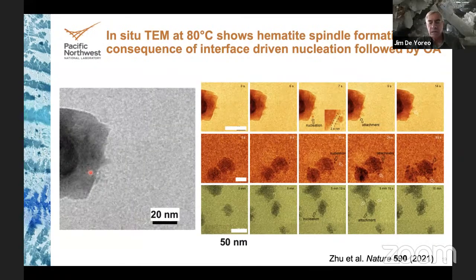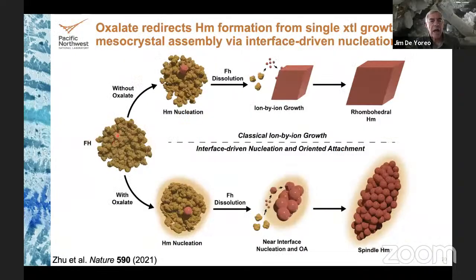attach to the surface. To show this schematically, without oxalate, somewhere hematite nucleates, the ferrihydrite dissolves away as the crystal of hematite grows through classical ion-by-ion growth to give beautiful single crystals. If you add sodium oxalate, as soon as a hematite particle forms, oxalate covers it. It can't grow larger, but it changes the local chemistry so that now hematite particles start nucleating around the existing one and start adding on. And apparently they nucleate more rapidly along the 001 axis than they do along other directions. And so instead of spherical, they're spindles.